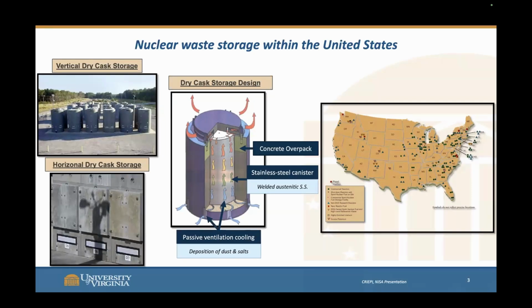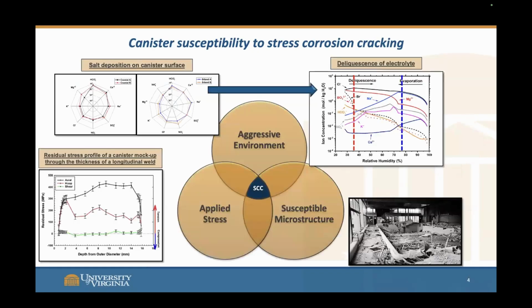And so nuclear waste within the United States is stored across most of the states. There's a lot of climate changes between all of these canister sites, and there's also going to be a lot of changes in what is being deposited on these canisters. And so we needed to look into this a bit more. These canisters are going to be susceptible to stress corrosion cracking. Specifically, one, we get this deliquescence of the salt deposits onto this canister.